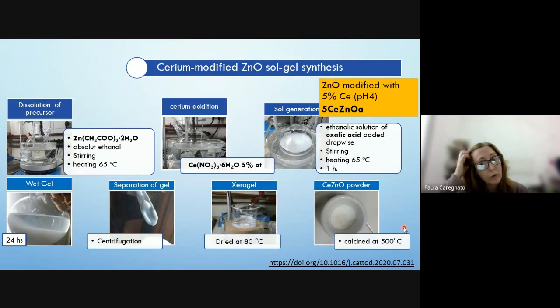The same material was modified with cerium by the same synthesis mechanism. Cerium nitrate was used with a quantity of 5 nominal atomic percent, and the sol was generated by adding the ethanolic solution of oxalic acid. The following steps are the same as in the synthesis of the material without cerium. This new material is named 5-cerium zinc oxide acid because it was obtained in acid media.